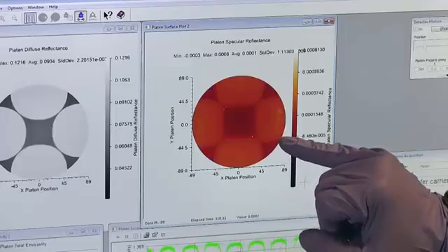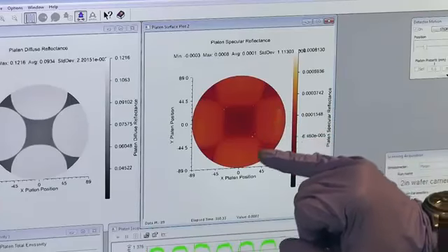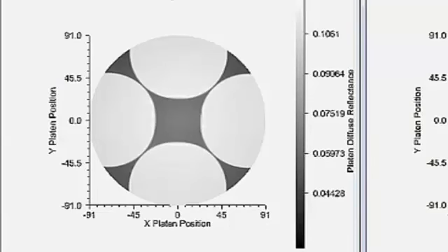If you look closely, I can also see what looks like machining rings in these pockets that the specular signal picks up. The diffuse signal is not as sensitive to those surface defects or surface qualities. However, the diffuse signal is really the main contributor to the total emissivity calculation.